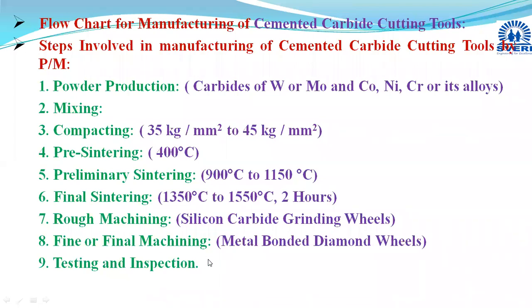That component's different properties like tensile strength, toughness, hardness, compression strength, microstructure, and amount of porosity, if any, are checked. Then its shape and size is inspected, and whether any kind of defect is there. All these are tested and inspected in this last stage, and after finding it with the optimum characteristics, that component is suggested for practical use. In this way, these cemented carbide cutting tools are manufactured.